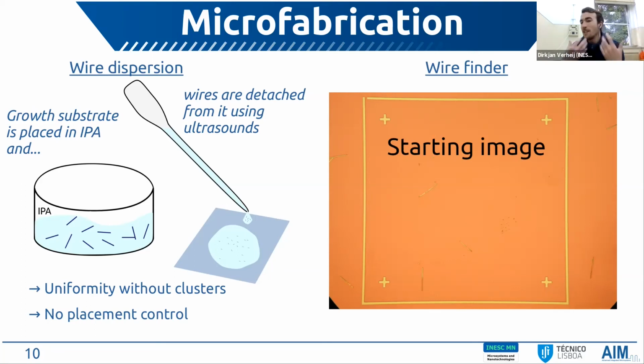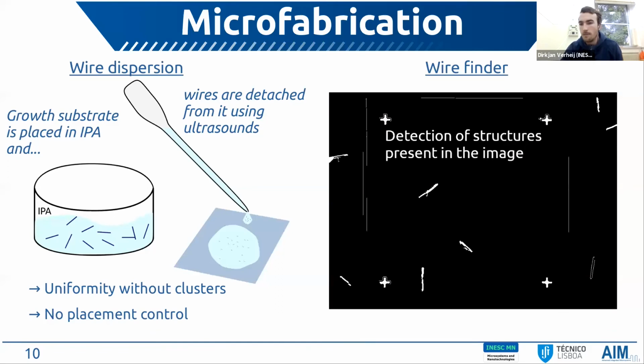So I need to find some way of balancing the time benefits and result benefit. But if the structures would be slightly larger, talking for example about 100 or even tens of micrometers, I think that this would be absolutely super reproducible, because these crosses are actually 12.5 micrometer by 12.5 micrometer, and they are perfectly defined in the image analysis software. So I don't think that would be a problem.